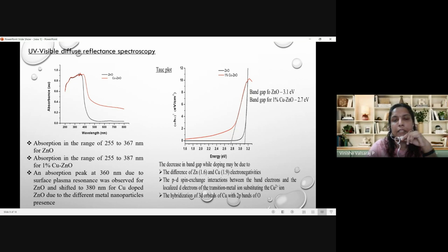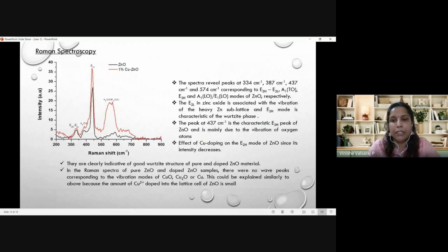Using the Tauc plot, we found the band gap of ZnO is 3.1 electron volts, and 1% copper ZnO is 2.7 electron volts. We can see that with copper doping, the band gap is decreased. The decrease in the band gap is mainly due to the difference in electronegativity of copper, and also the sp-d spin exchange interaction between the band electrons and the localized d electrons of the transition metal ions substituting Cu2+.